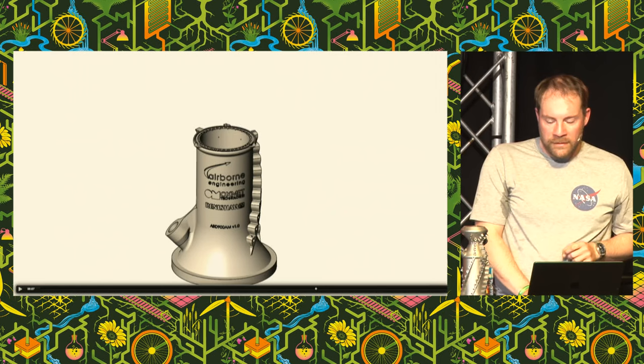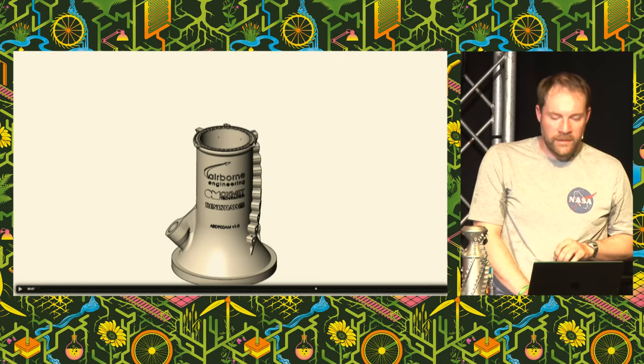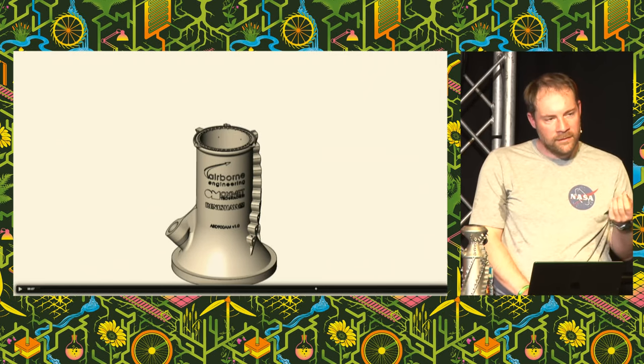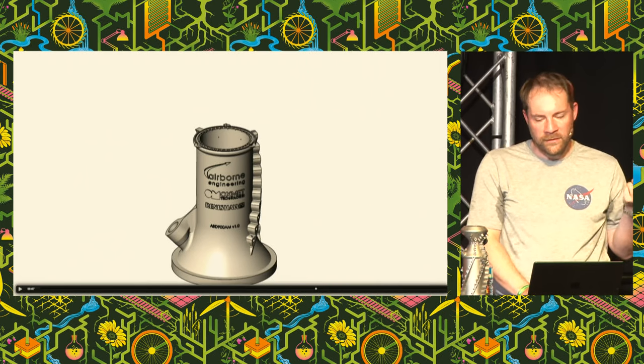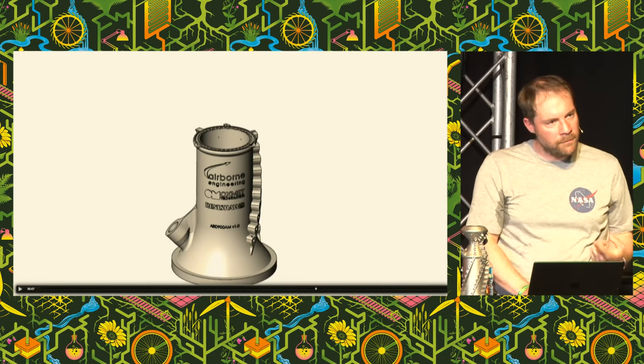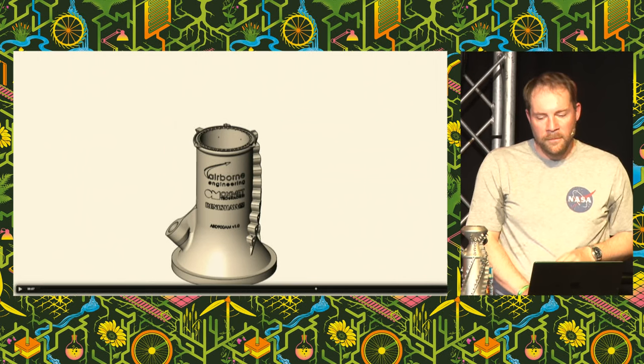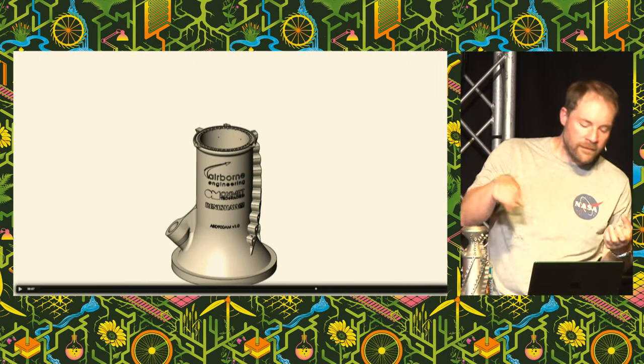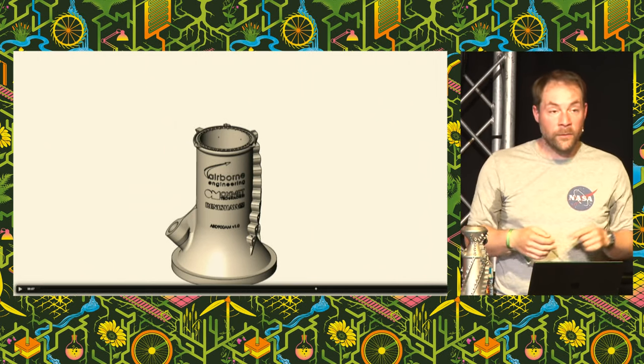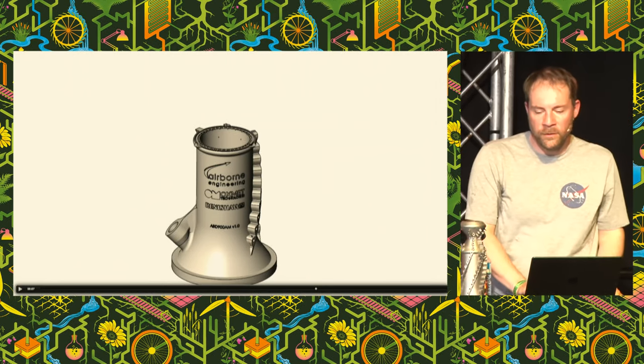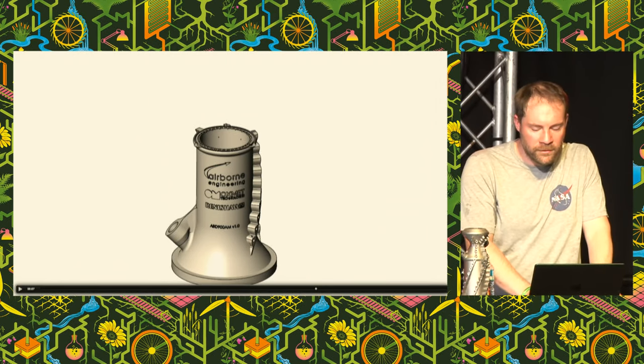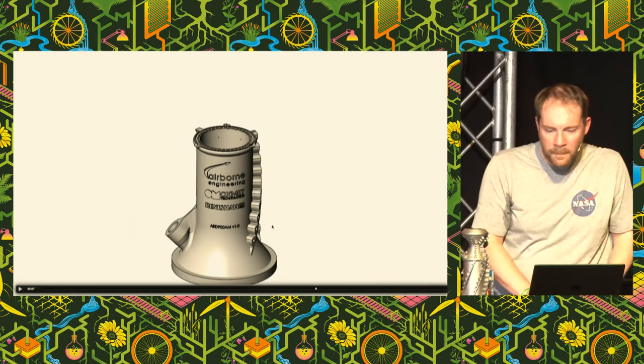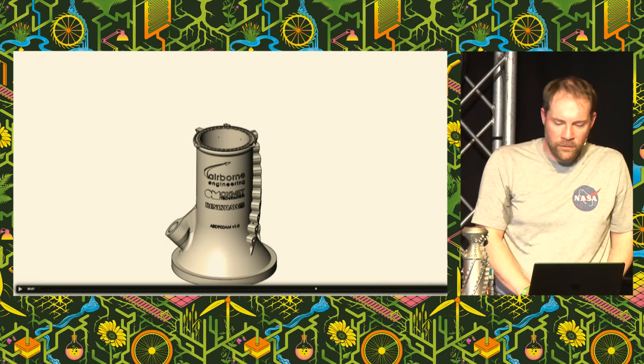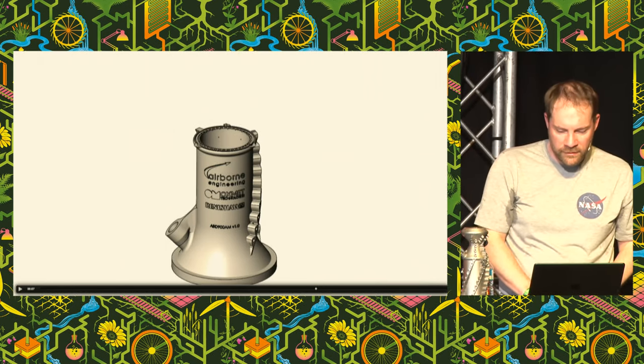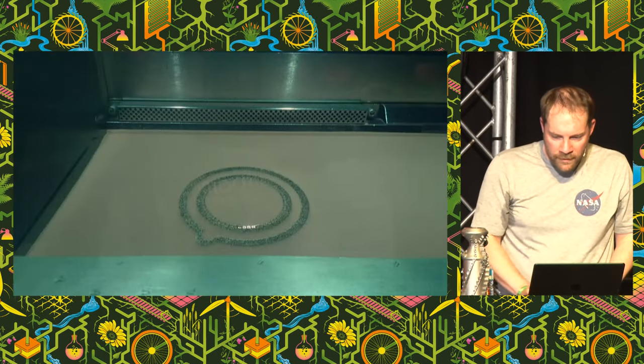One of the particular things with metal 3D printing is that the surface it leaves is slightly rough, and that causes quite a lot of loss of pressure when you pump a fluid down the cooling channels, which means you need to pump fluid in at even higher pressure, which is a bit of a drawback, because it's quite hard to pump fluids at really high pressures in rockets, especially when you need your pump to weigh as little as possible. So we're measuring the pressure losses down the channels and the temperatures into the channels.